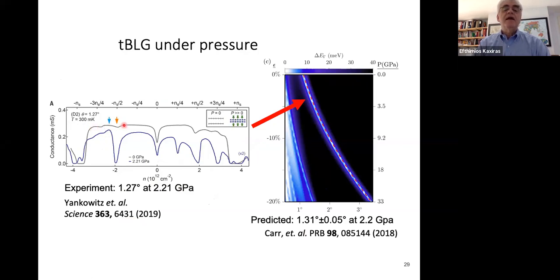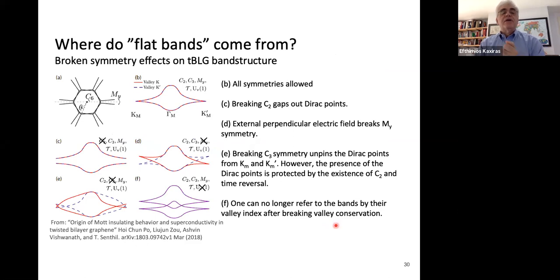And here are the two different measurements. The gray line is at zero pressure, zero gigapascal. The blue line is at 2.21 gigapascal. The twist angle is 1.27 degrees. And the blue line indicates this behavior characteristic of the superconducting or flat band structure. So at 1.27 degrees, it takes 2.2 gigapascals to create flat bands. And this is exactly what our theory was predicting, or very, very close to what our theoretical predictions were. So the million-dollar question is, where do these flat bands come from? And this is not an easy question to answer.